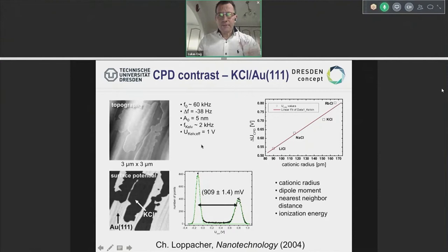We can really get quantitative access to a lot of chemical information of this surface on non-conductors. The example here shows, for instance, a potassium chloride surface on gold. You see nicely in topography some islands, and you can say, okay, it's going up, it's going down, but who is who in this new graph? We don't know. So what you do is hook up your Kelvin probe measurements with a 2 kHz sideband modulation, a 1 volt modulation, and then you see nicely that the surface potential, this delta phi, gives you a huge contrast between black and white, which, if you go for statistics, is really two peaks. One peak at this position is the potassium chloride, because it's darker, it's lower in voltage.